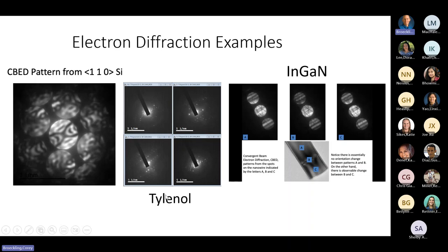Then we can go to a fun thing. This is Tylenol. Go to your grocery store, buy a bottle of Tylenol, bring it to the lab, we'll crunch it up, put it in a microscope, and you can get diffraction patterns. This has become a big thing in the pharmaceutical industry. Big difference here is with x-ray diffraction, you need a sample that's moderate size, several microns. We can go to nanometers effectively and get this diffraction. They call it micro-ED, microelectron diffraction.